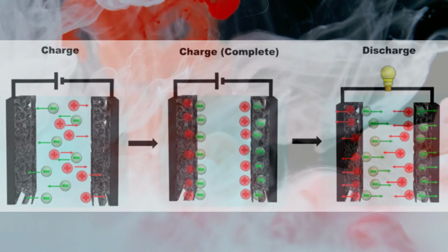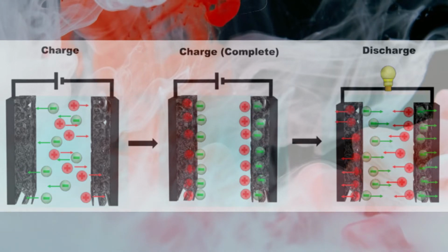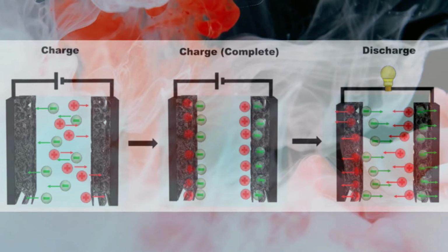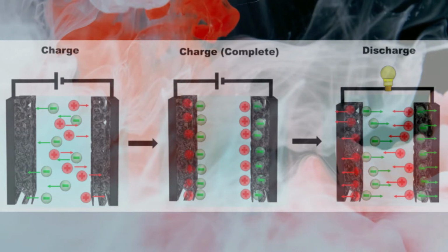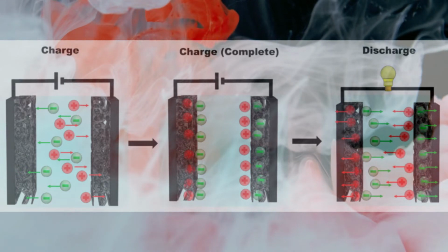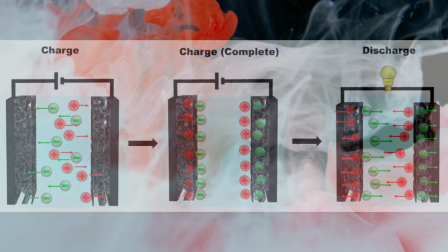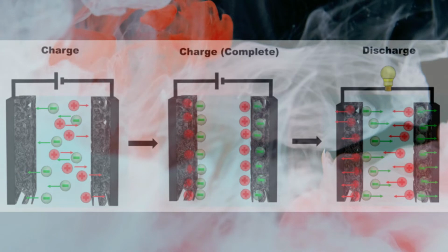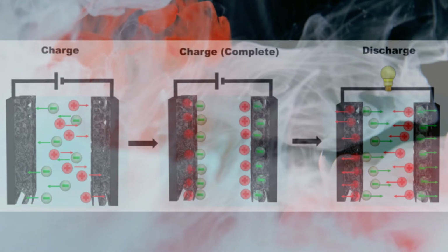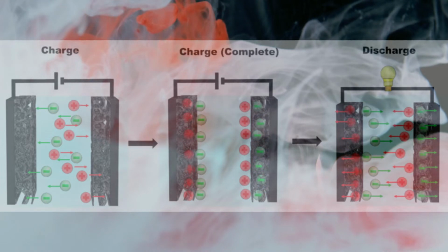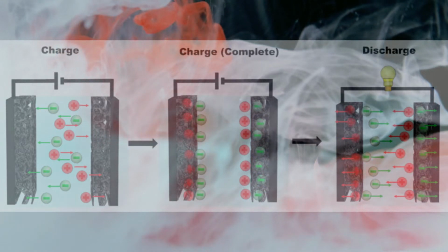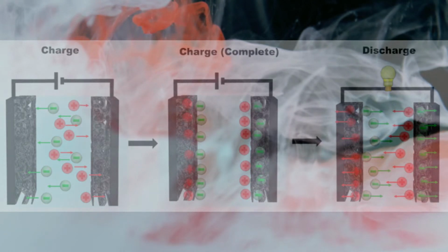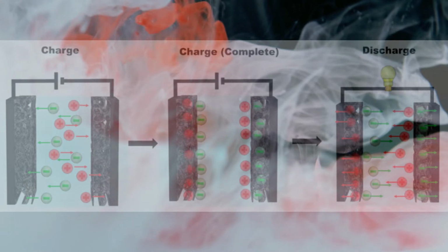Cellular graphene, providing high electrical conductivity, a large surface area, and fully interconnected porous geometry, has attracted widespread interest as a support for complex three-dimensional, 3D, graphene hierarchical architectures. However, some limitations inhibit the potential of this carbon material as a building block for larger applications. Because of their irregularly distributed porous microstructures, cellular graphene maintains a low stretchability, proving to be a drawback for wearable applications. The material's electrochemical performance is also dramatically affected by mechanical deformations under moderate levels of strain, limiting its viability in emerging wearable energy devices.